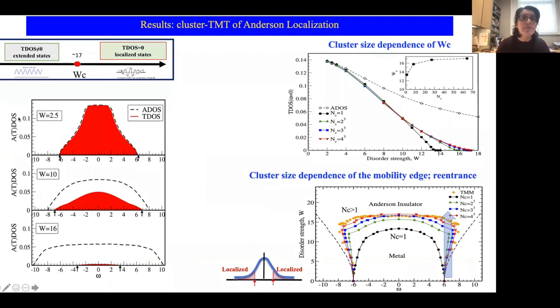So on the left, I'm showing you the evolution of the average and the typical density of states as a function of disorder strength. Average density of states is shown in dashed line and typical is shown by the shaded region. As we would expect, below the transition, typical and average will be finite, but above the transition, we expect that the most probable or typical value will go to zero, and that we will see in our calculation. While the average density of states will stay finite no matter what, right? And indeed, this is what we see.